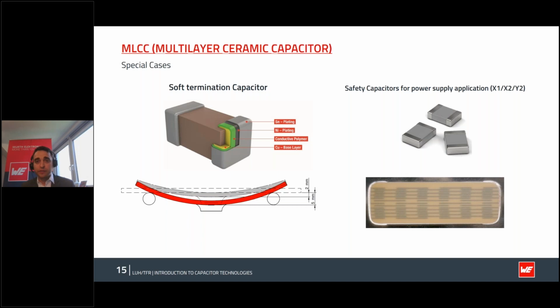Normal parts can be bent on a 10 centimeter PCB down to 2 millimeters, and these soft termination capacitors can be bent 5 millimeters on the PCB. Apart from that, there are also safety capacitors, with X1, X2, and Y2 safety classes. I'll define them in a minute together with the film capacitors. And you can see on the right, the internal structure is basically multiple capacitors in series. This way, we can limit the likelihood of the failure mode ending up in a short circuit.